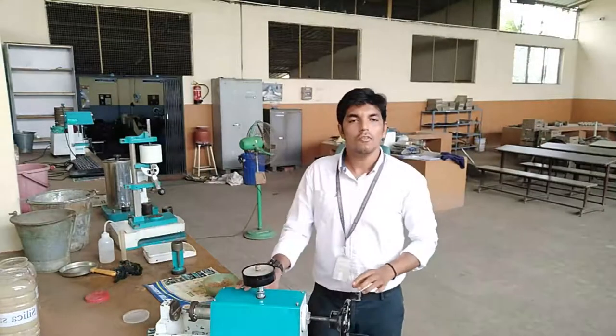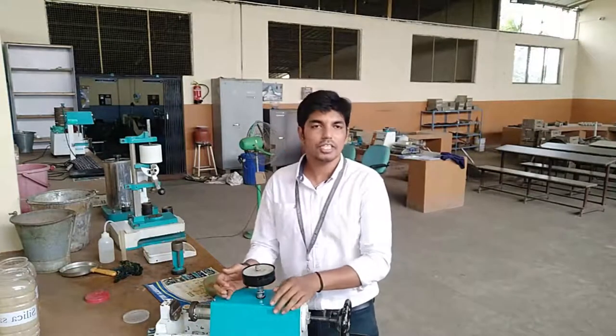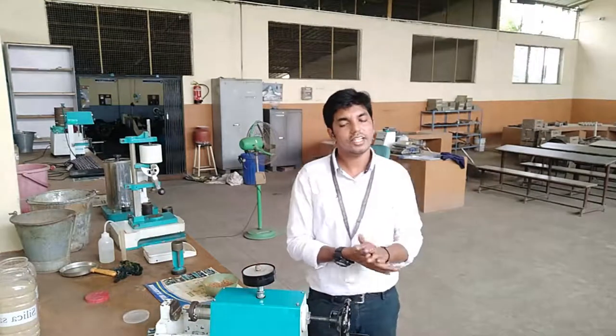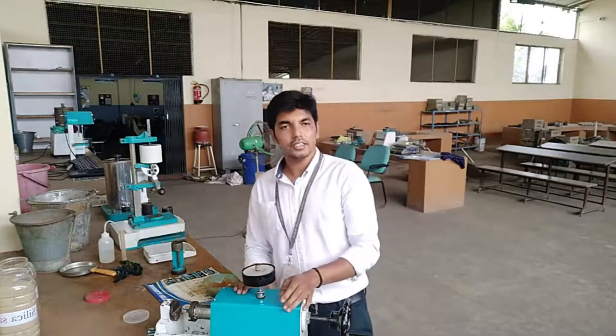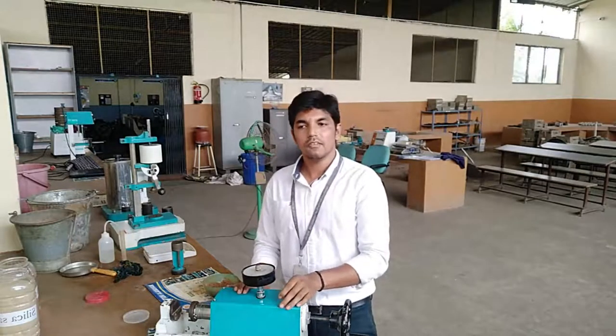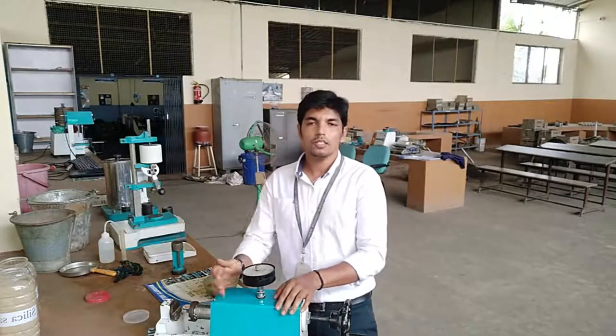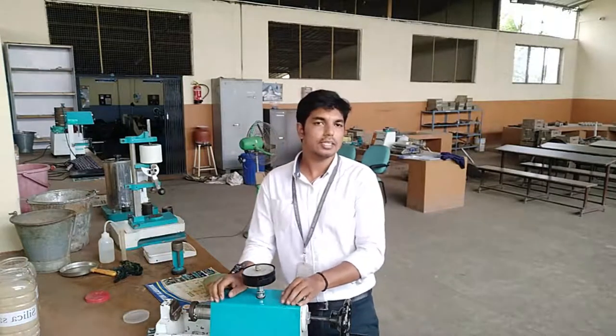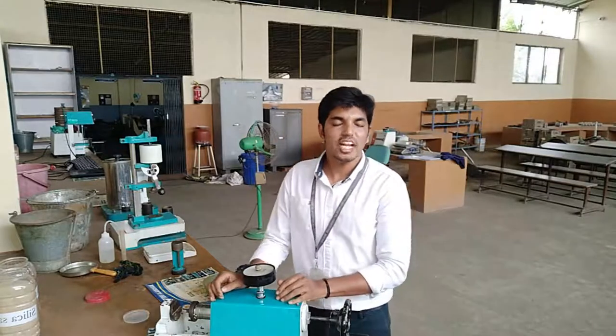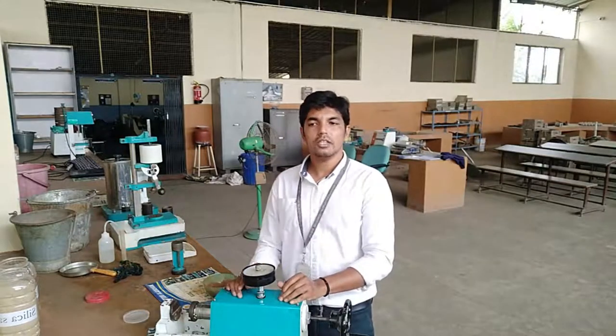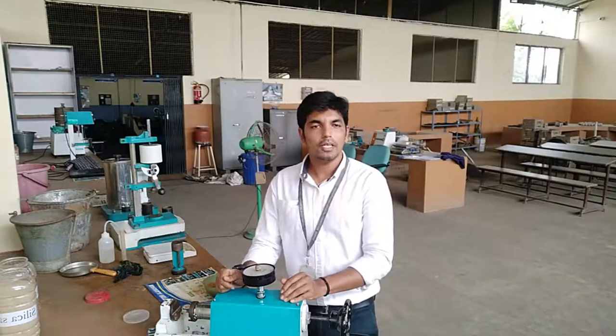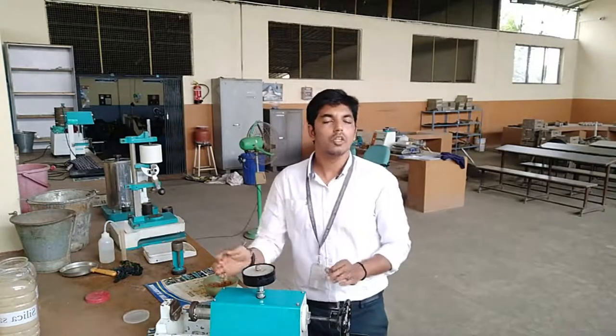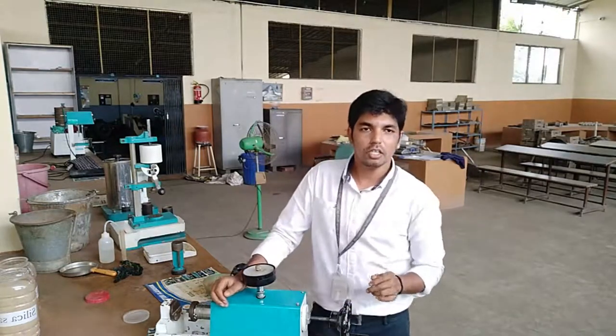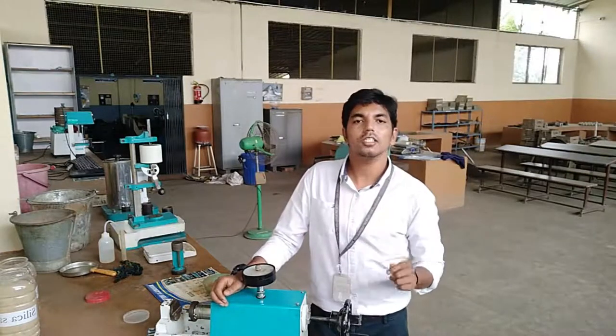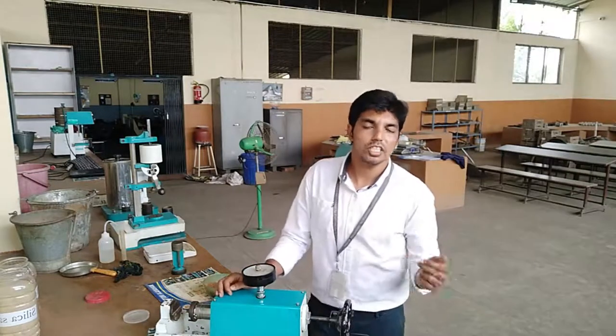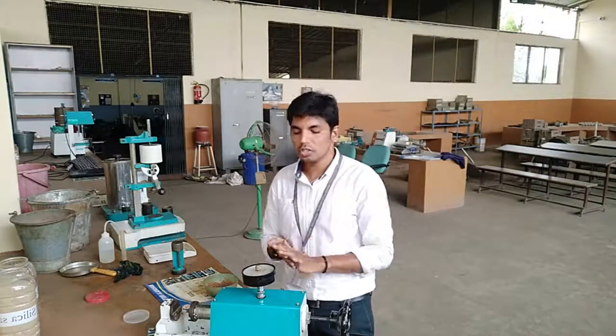Welcome back. Now we are moving on to the second trial of the shear test. In the second trial, we need to take the same amount of clay binder, 15 grams, and 135 grams of silica sand, but here the percentage of water is increasing from 8% to 10%. So 8% of water is 12 ml, but 10% of water means 15 ml. So I need to check what the shear strength will be if the percentage of water increases from 8% to 10%. Whether the shear strength is increasing or decreasing is noted down with the help of the dial gauge.